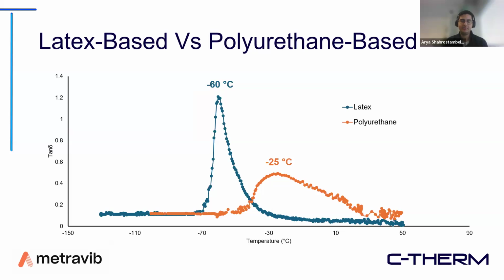So here are the test results from a temperature sweep on condom materials. The blue line shows the latex-based, and the orange line shows the polyurethane-based condoms. Again, we can see the tan delta quantity on the y-axis, and there are peaks. The peak on the left-hand side with the blue line shows the latex condom glass transition temperature, which is at -60, and for polyurethane it shows -25.